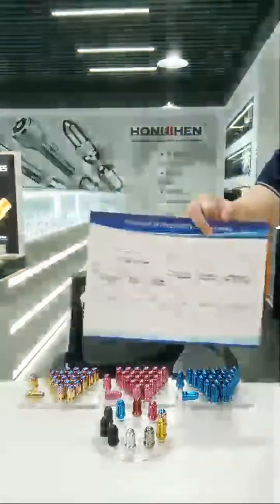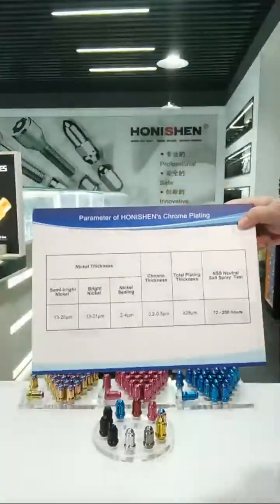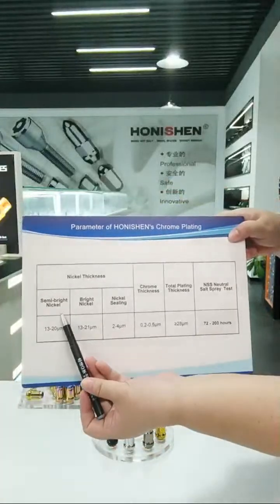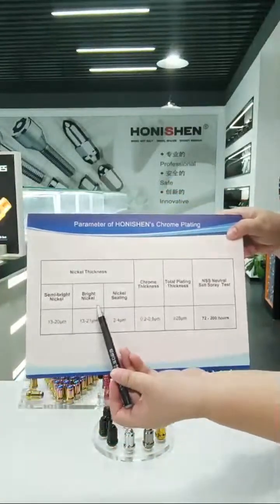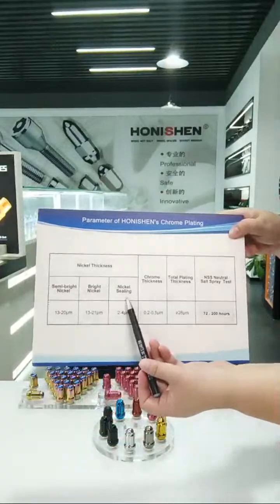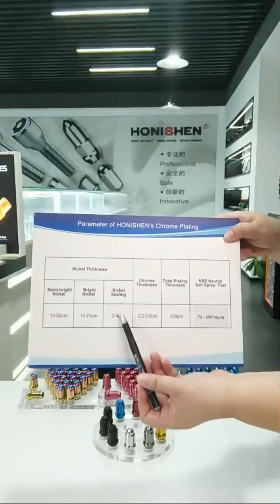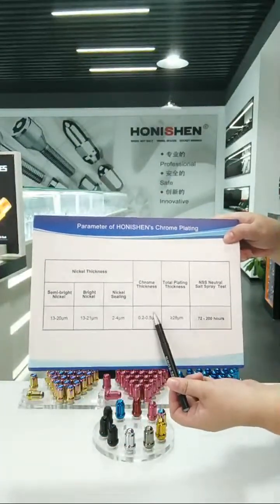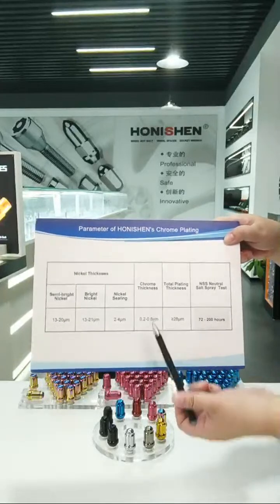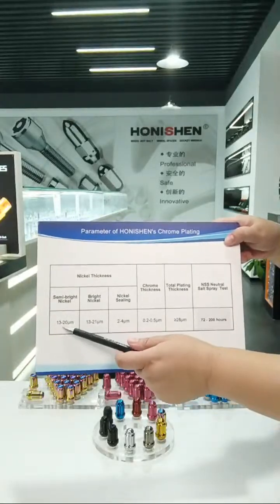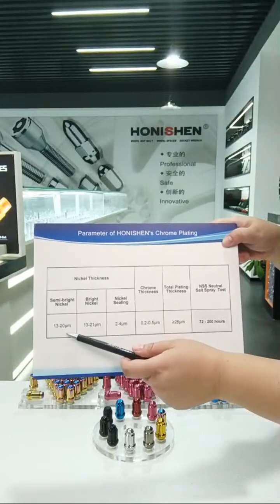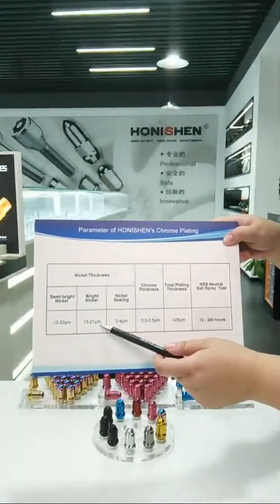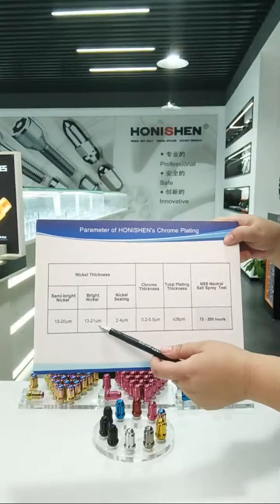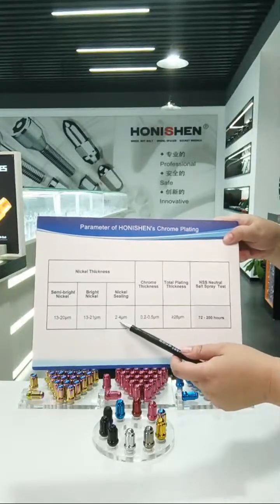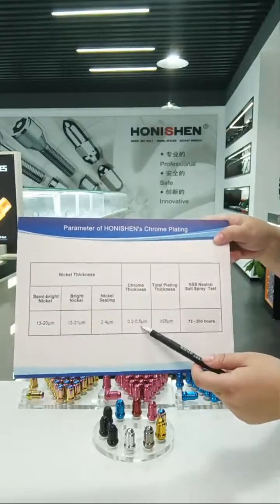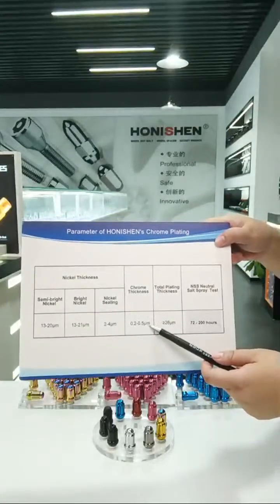Our chrome coating consists of 3 layers of nickel. One is semi-bright nickel, 2 is bright nickel, and 3 is nickel sealing. 3 layers of nickel and 1 layer of chrome together. So we promise the semi-bright nickel is 13 to 20 micron, and bright nickel is 13 to 21 micron, and the nickel sealing is 2 to 4 micron, and chrome is 0.2 to 0.5 micron.